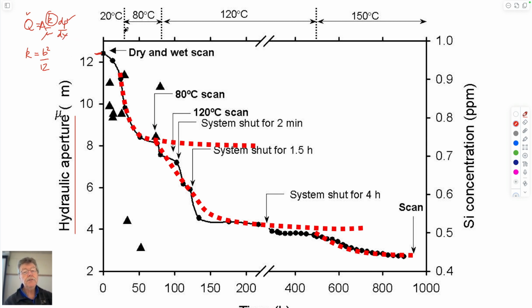And the only thing that's done to this is the temperature is increased. And as the temperature is increased, the dissolution of silica out of the system rises. So there's a finite dissolution of silica. So this references this side here. And as you increase the temperature, you measure a change in permeability in the system. So this is the curious thing. Again, the reason for doing experiments. Why, if you're net dissolving material from the porosity, does the permeability go down if the porosity should be increasing if you're net dissolving material from that?